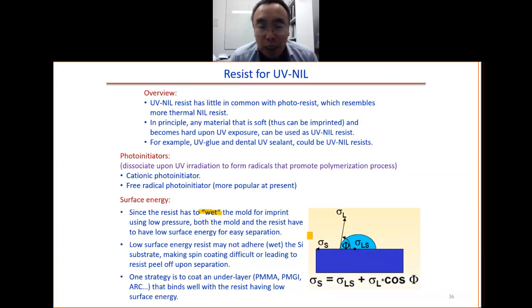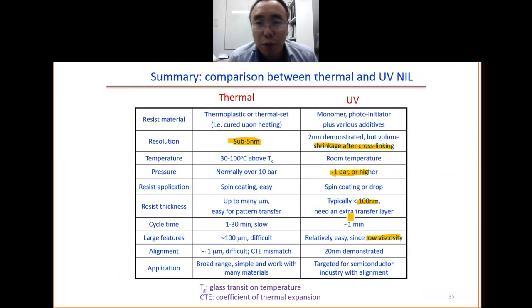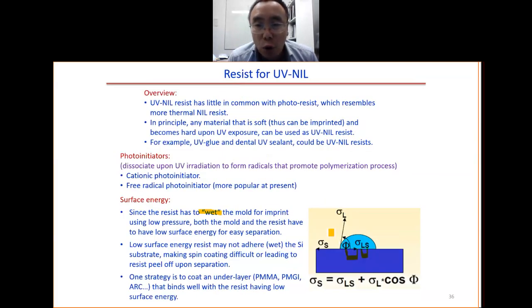When it wets, in principle, you do not need any pressure because the resist will fill in the pattern on the mold by the capillary force. It will get in by the capillary force. You do not need to apply any pressure. But in reality, you will need some pressure, like 1 atmosphere, to make sure that the mold and the wafer have good contact. So the pressure is needed only to make sure you have good contact, not to squeeze the liquid into the pattern on the mold, because they wet each other.